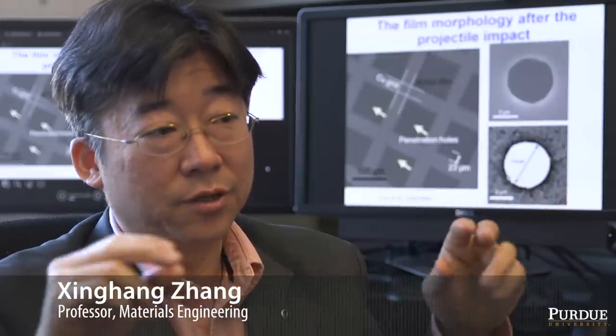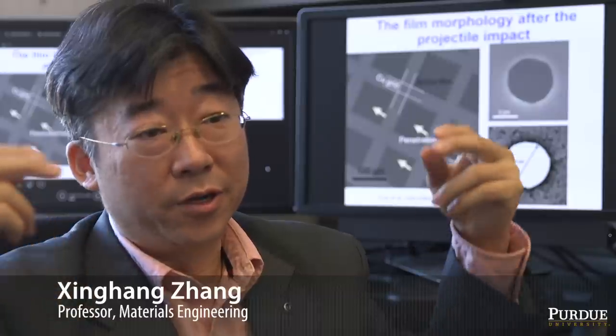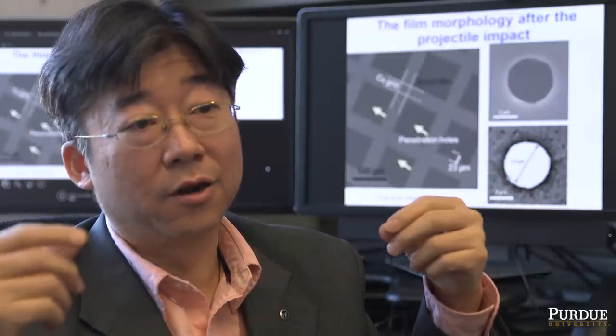We identified super-long stacking faults in aluminum. And these super-long stacking faults, they have nine repeating layer structure. So this is so-called a 9R phase.